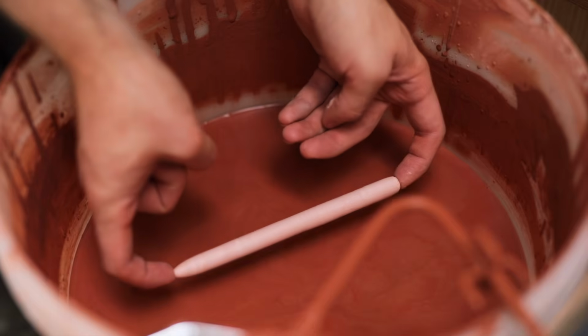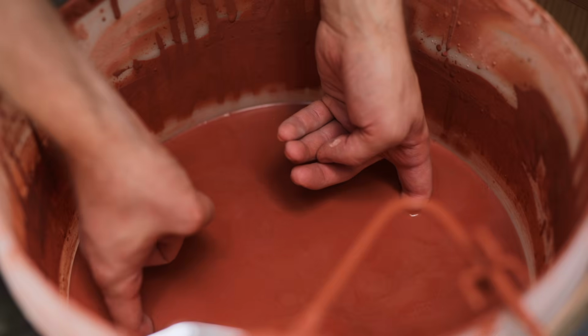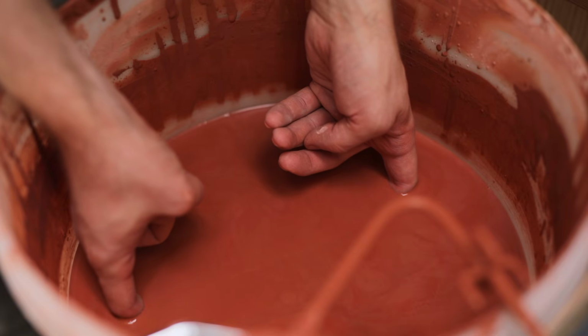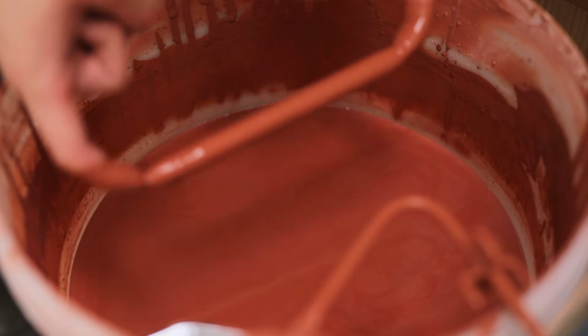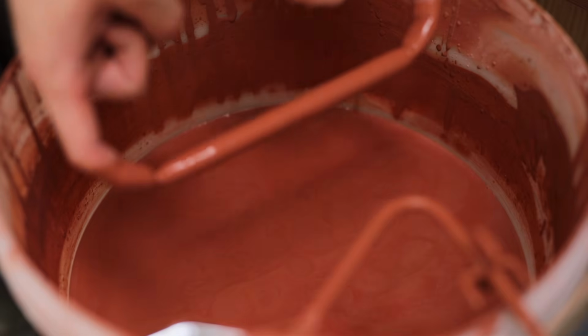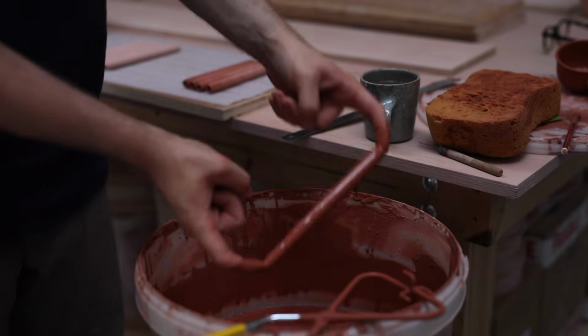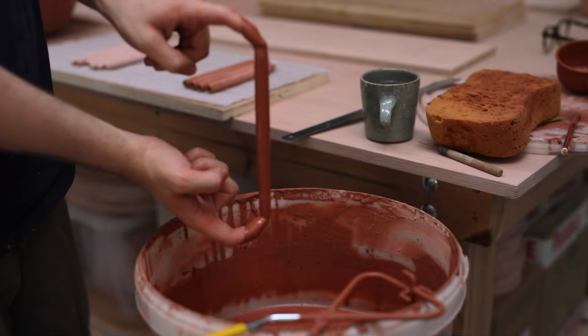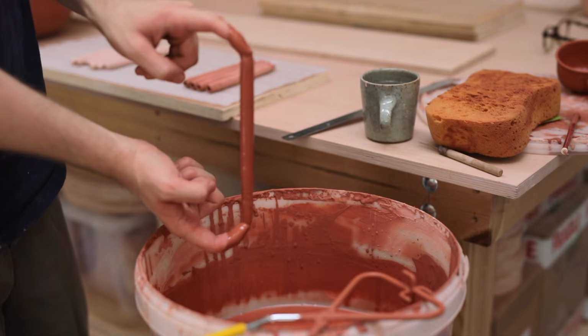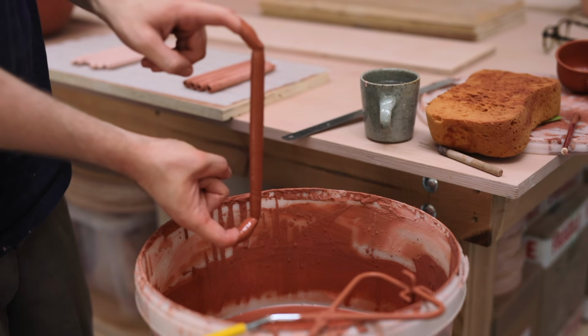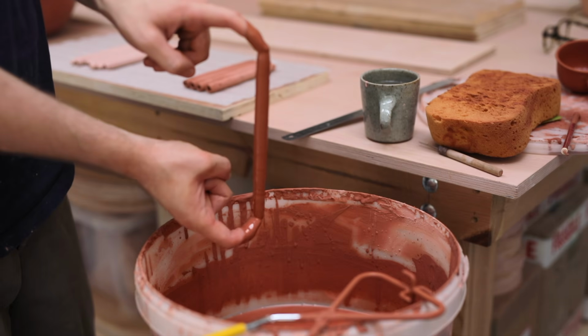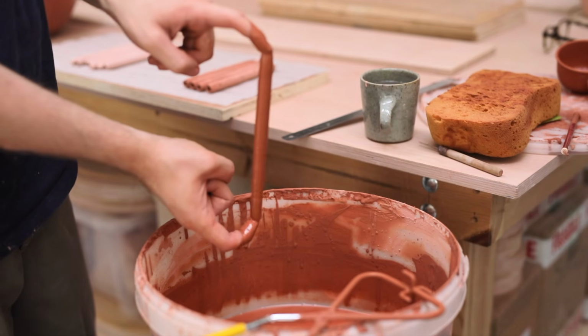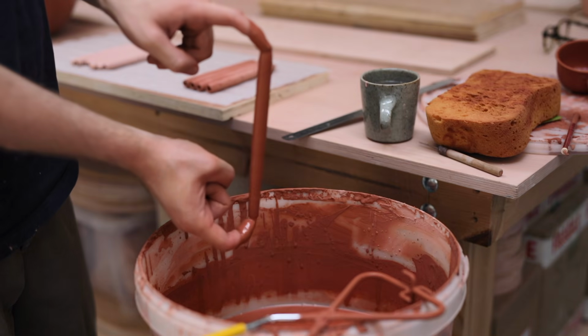So to glaze these, I simply hold them at each end with one finger, and then submerge them for about 5 or 6 seconds. They're then removed, and I let the excess glaze drip away, as I can't immediately touch them or put them down as the glaze is still wet. I have to hold them and wait until the surface dries enough that I can touch it, so that I can hold it from the middle without damaging the freshly glazed surface.